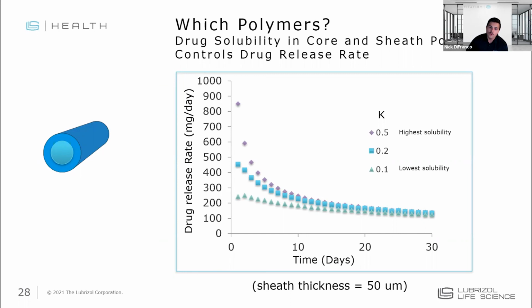And when you think about core sheath implants, solubility in the core polymer versus the sheath polymer can have a major impact on how quickly the drug leaves that system. In an implant where the API is not very soluble in the sheath polymer, you achieve a much slower release rate, closer to zero order. But of course, if you're selecting polymers and prototyping with polymers in which the API has a higher solubility, you're going to get faster release, closer to first order. So just another factor to keep in mind when designing these systems.